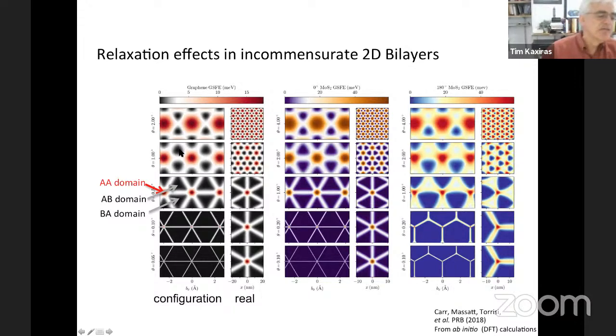And you see different panels here. As you go down the column, you start at 2 degrees twist, 1 degree, and then smaller twist angles. But you see that the pattern in real space at large angles is very confused, so to speak. There are no clear regions here. At 1 degree, the regions start to appear, and if you go to smaller twist angles, the pattern does not change, only the black regions increase, and everything else stays the same. So you just expand the scale of the system, but nothing else changes. This is indicative that at around 1 degree, these regions have fully appeared, and they don't really change character anymore. They just change size.